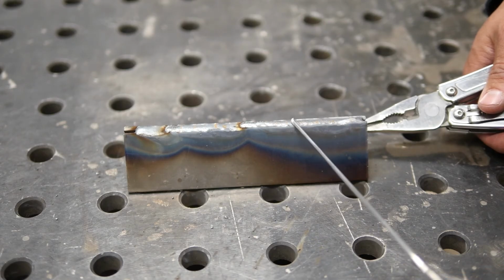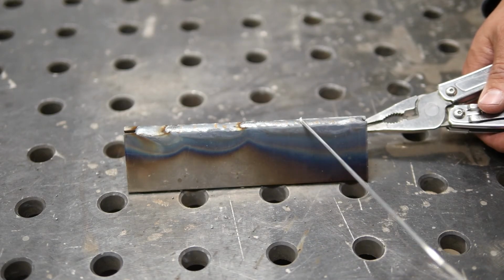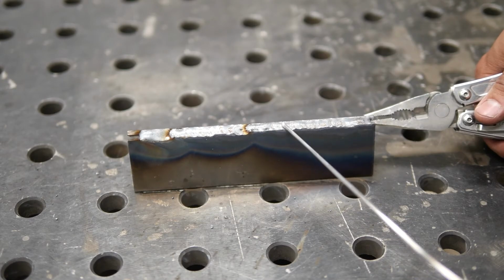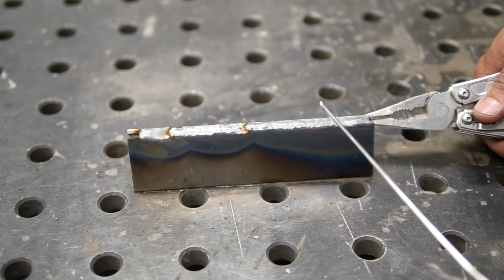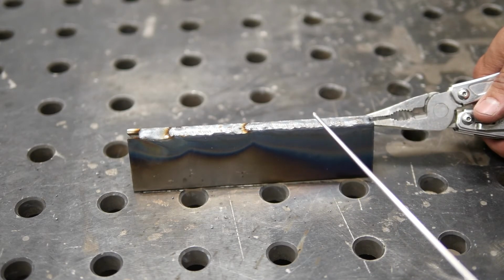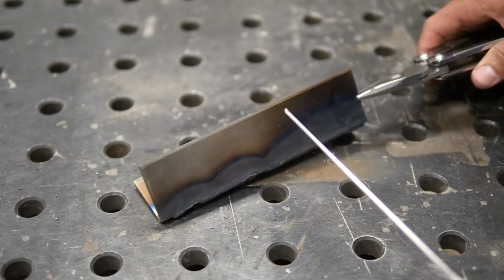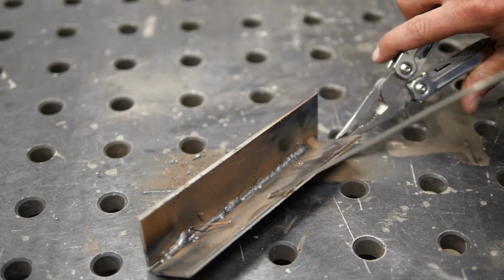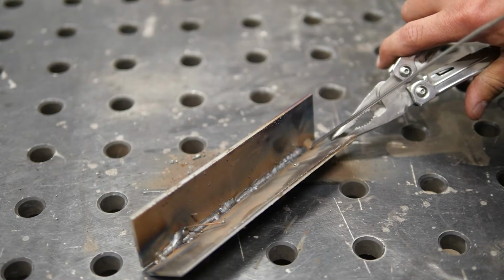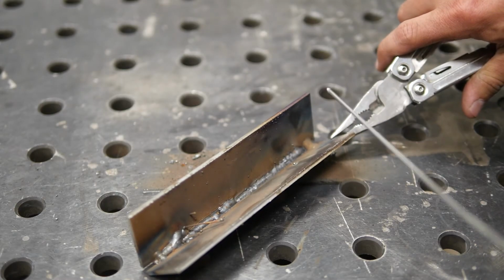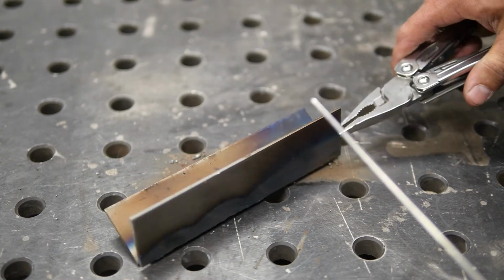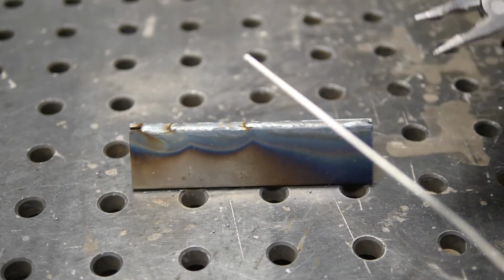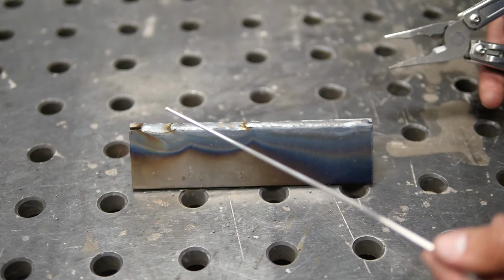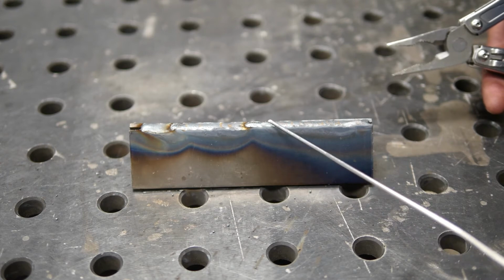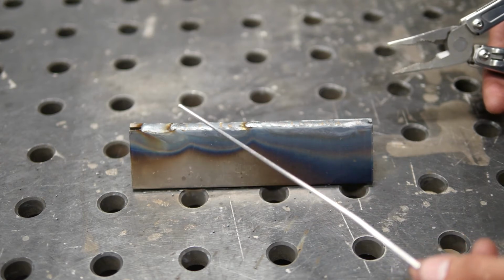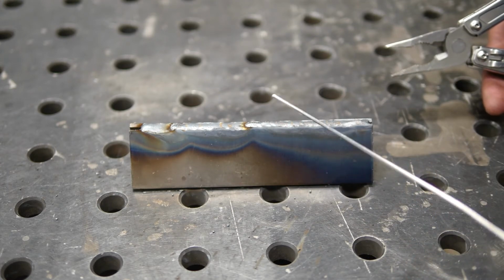130, 100, and now I'm starting to get the results that I want. I really don't need a lot of penetration here because there's already an open root. There's a gap in between the material. So if we flip it over here, we can see it got plenty of penetration on the backside. What I just don't want to do is blow through or put any excessive heat into the plate unnecessarily. So this proves that wire feed speed is penetration. If I leave it at that higher wire feed speed number, it's just going to keep pushing through.